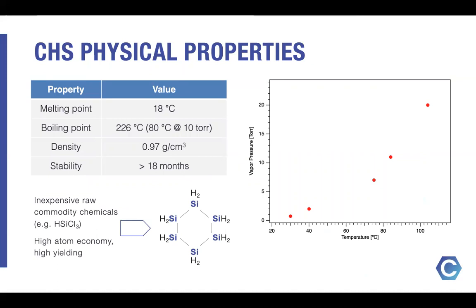Taking a look at the physical properties, CHS melts right below room temperature, so it's a liquid at room temperature. It boils at 226 degrees, and relatively low at modest vacuum: at 10 torr, it boils at 80. When stored under inert atmosphere, we have strong evidence that it's stable for at least 18 months. CHS is made in 2 steps from inexpensive commodity chemicals such as trichlorosilane.